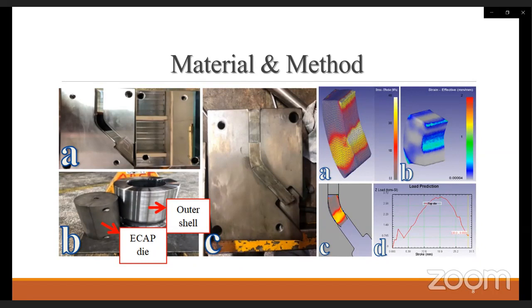Two male punches were plastically deformed, however, the samples inside the channels did not even move a bit. Then the ECAP die set is disassembled from the outer shell, and the samples stick inside the channels as shown in the middle photo. The billets are stuck inside. It's not possible to take them out. During the cleaning of the samples stuck inside the channels, too much force is needed to be applied for the samples to pass through the turn. So it was nearly impossible to take these two billets out.